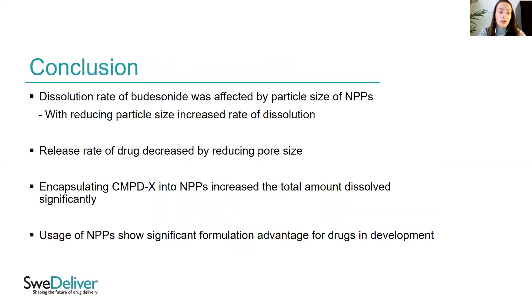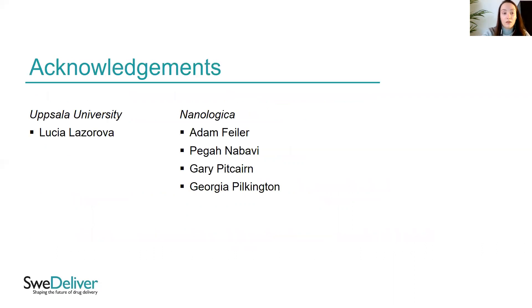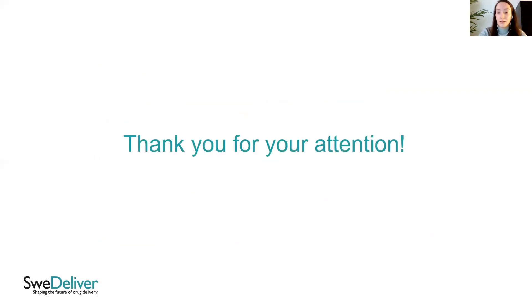In conclusion, the dissolution rate of budesonide was affected by the particle size of the nanoporous particles — reducing particle size increased the rate of dissolution. The release rate also decreased by reducing the pore size, and encapsulating the highly insoluble CMPD-X into nanoporous particles significantly increased the total amount dissolved. The usage of NPPs shows significant formulation advantages for drugs in development. I would like to thank the people who helped during the project, and thank you for listening to my presentation.